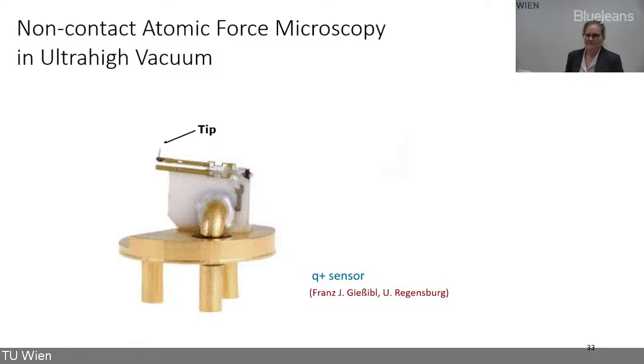Now, there's a method that's kind of the hot new kid on the block in surface science, this non-contact atomic force microscopy in ultra-high vacuum. Atomic force microscopy is a very well used technique, but in ultra-high vacuum it's only in the last 10 years or so that it's really taken off, thanks to this qPlus sensor invented by Franz Giessibl from the University of Regensburg, where one mounts an STM tip on a piezoelectric tuning fork that oscillates with its own resonance frequency with a very high quality factor.